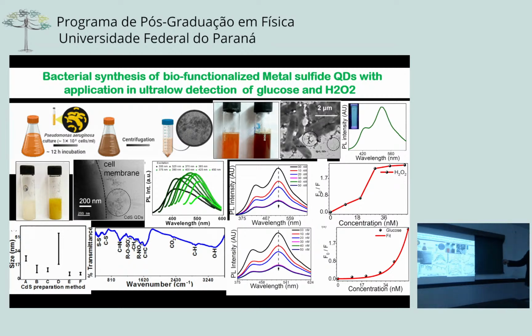If you come back, what you see is the color of the solution has changed. If you do a centrifuge, collect the powder and do analysis, we are able to produce metal sulfide or cadmium sulfide quantum dots. I'm not going to go into detail, but just quickly, what we want to highlight here is these are microbes, and if you look in a transmission electron microscope, just on the surface of these microbes, you see these small quantum dots.